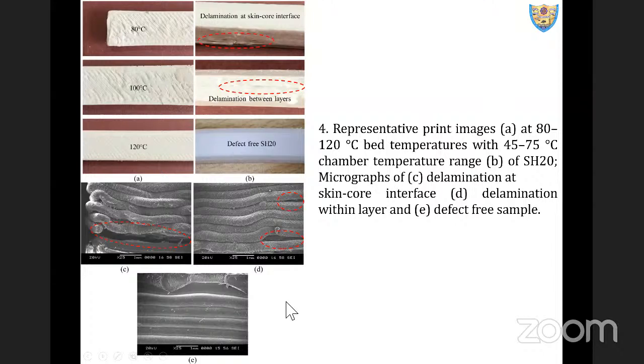So the chamber temperature plays a vital role as well in controlling the delamination at the skin core interface, the marked one here, or within the layers, the marked one here. So this is what the defect-free sample came out as, based on the permutations and combinations. And this is how it looks in scanning electron microscopy. When you take an SEM onto the edges of the bad ones, you can see clearly the skin and the core are separated at this interface. There are some intra-layer gaps as well. But once you tune these parameters, you get perfect bonding between these layers.